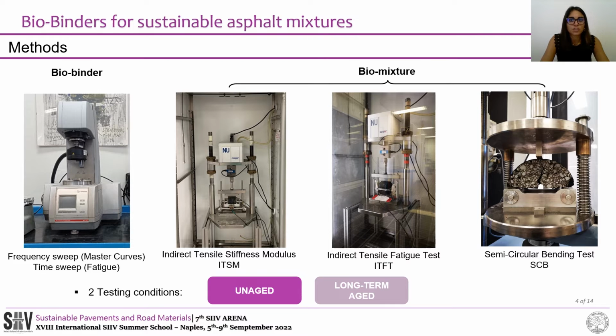Then, a conventional mechanical investigation consisting in indirect tensile stiffness modulus, indirect tensile fatigue test, and semicircular bending test was performed on asphalt mixtures. Both unaged and long-term aged conditions were investigated.